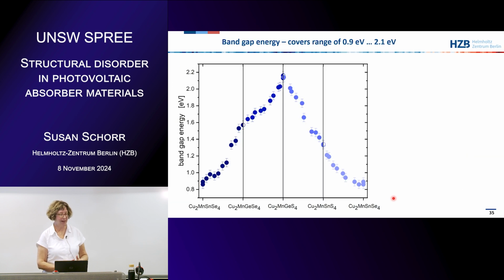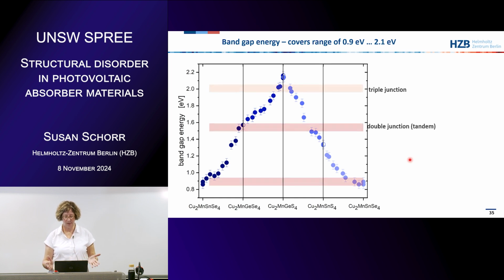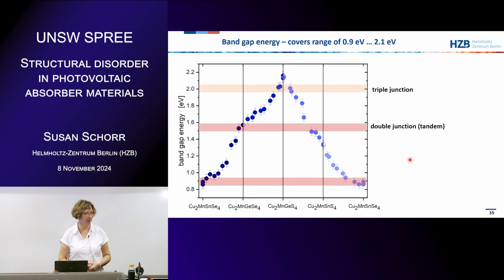What about the band gap range you can cover with this series? In principle, you can go from 0.9 electron volt, you mix and mix and mix, up to 2.1 electron volt. And then, of course, it goes down depending on which mixture you obtain. So in principle, these materials could work for a double junction or triple junction solar cell material. So you can cover a quite large band gap range.